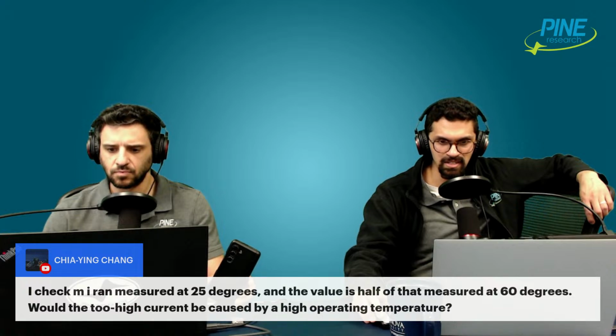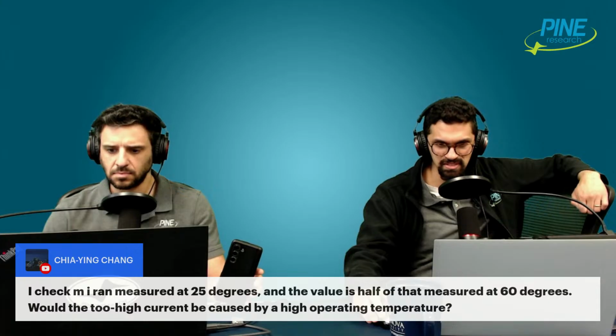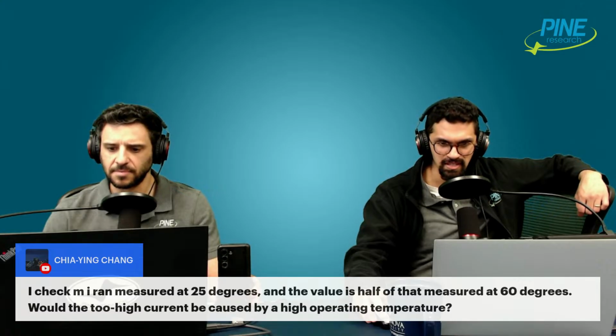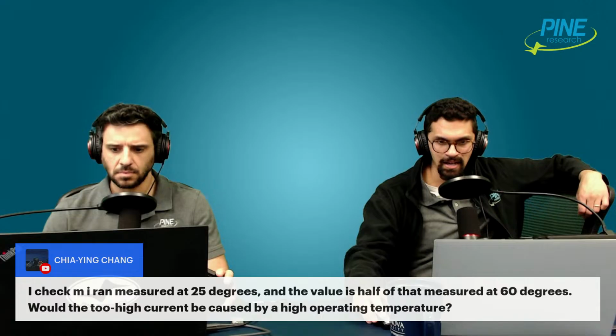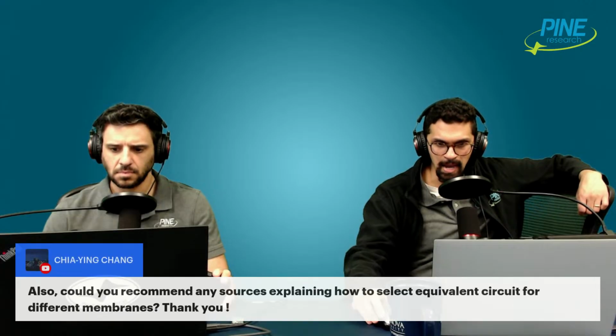I checked, I ran the measurement at 25 degrees, and the value is half of that measured at 60 degrees. I don't know what the degrees are in this. I assume Celsius. Oh, this is temperature. Okay, yeah, right, temperature. The value is half, that would be at 60. Would the too high current be caused by a high operating temperature?